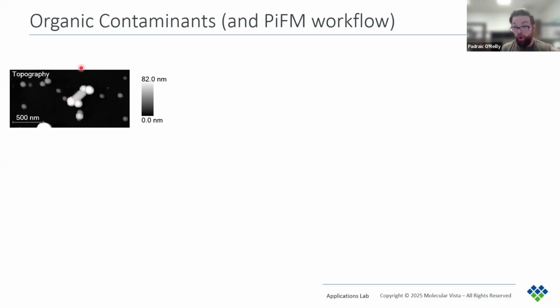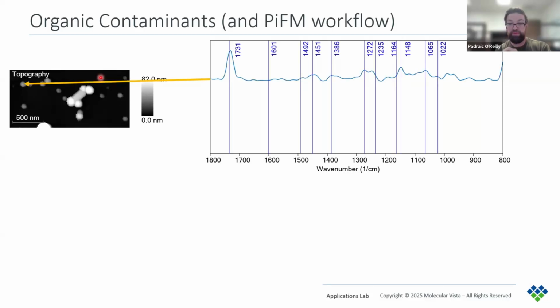You can take spectra on all of them, or you could use chemical mapping or PiFM imaging, as is the term we use, to speed this up, especially if you have a large number of contaminants. You don't want to be taking spectra on every single one. So let's start with taking a spectrum on one defect. And here we see we have multiple peaks for this defect. We can select one of these wave numbers to take a PiFM image. In this case, we'll use the strongest peak, around about 1730 here.